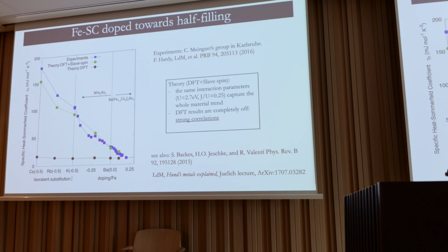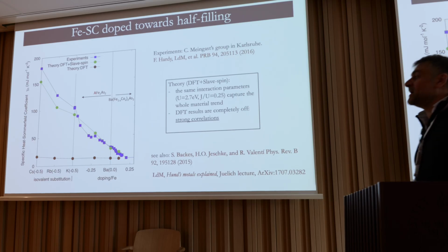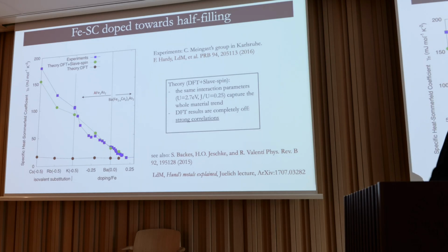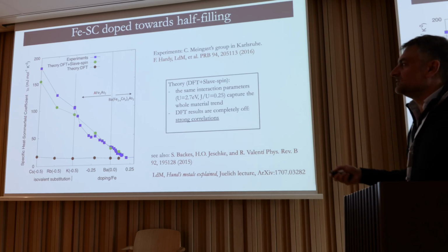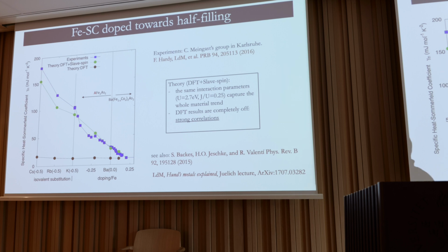Here we use only one value of the interaction and then just change the doping. So it's really the doping which is increasing the correlations more and more. And if I take away the Hund's coupling, this behavior goes back basically to the value of DFT. So it's really Hund's coupling which is the key player giving these correlations here.